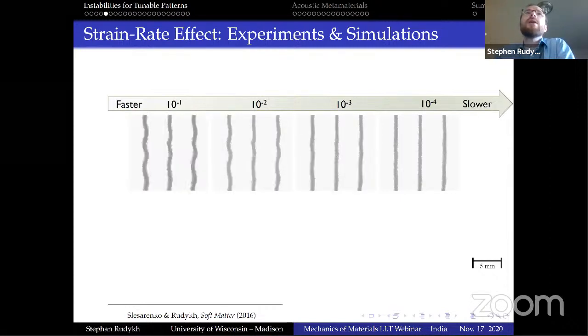And you can see that for this one that we loaded much faster, we were already exerting the viscoelasticity in the layers, while the viscoelasticity of the matrix is rather weak, again, compared to the layered material. So we can already obtain the developed instability here, while the same level of deformation with the same identical material is still stable and the layers are still flat.